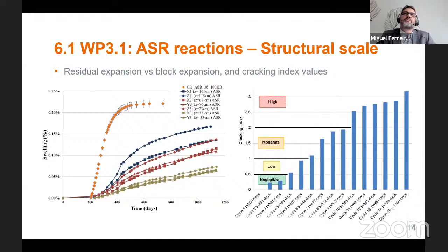And here we have some more results, and these are of the expansion of the block and the residual expansion tests, and also the cracking index. So if you look at the blue, red, and green curve, we see the expansion in different heights. We had sensors at the lower third, we had sensors at the mid height, and we had some expansion sensors at the upper end of the block. And we can see that as we go from the base to the upper end, the expansion increases in all 3 directions.